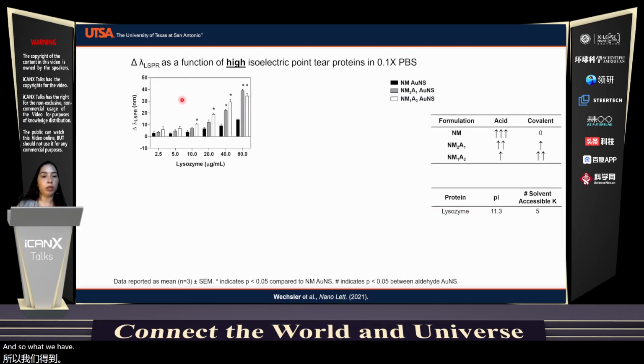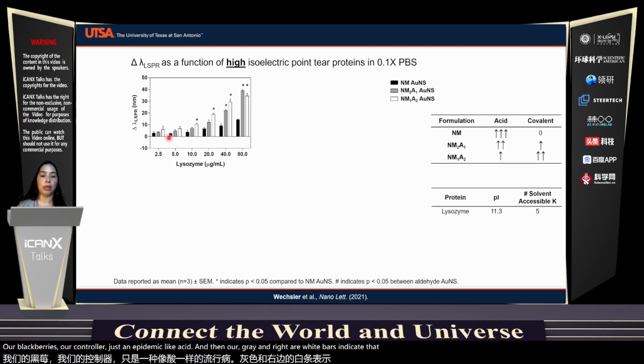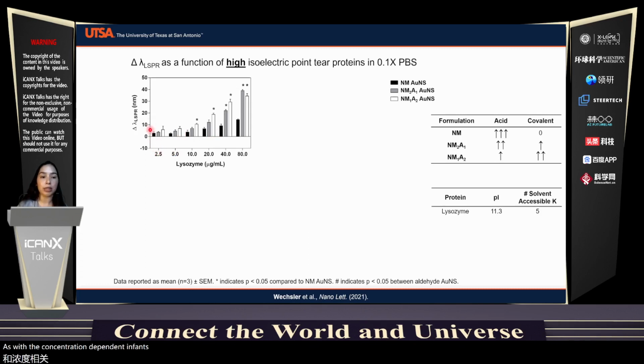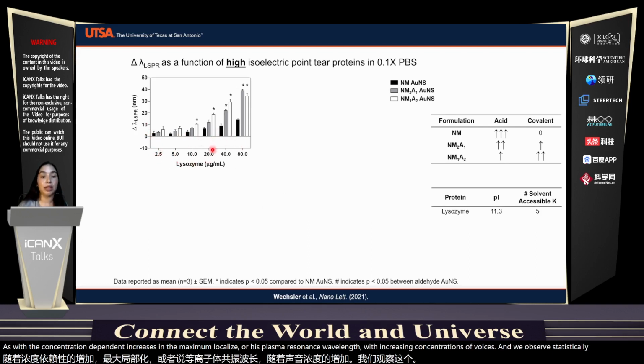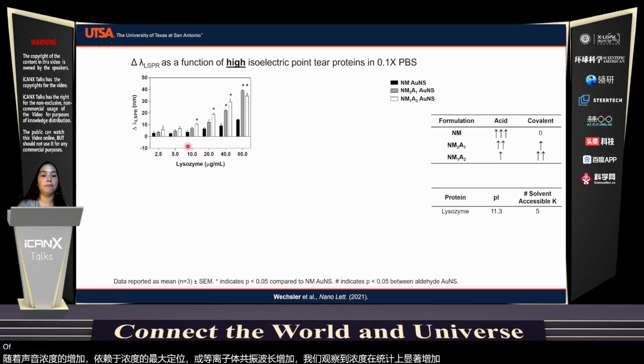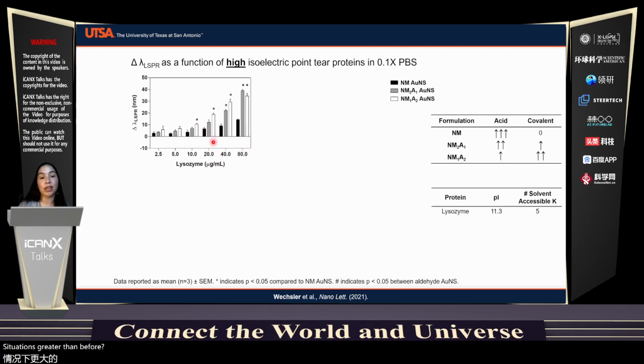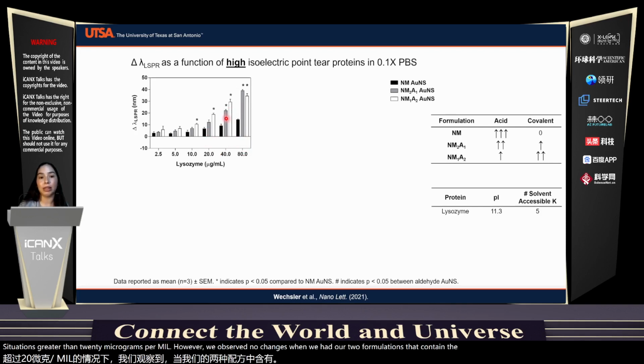And so what we observed in this first graph here is the delta localized surface plasmon resonance as a function of lysozyme concentration. Our black bars are our control, just the NIPAM methacrylic acid, and then our gray and our white bars indicate our increasing component of our covalent monomer incorporated into the polymerization scheme. And so we observe concentration-dependent increases in the maximum localized surface plasmon resonance wavelength with increasing concentrations of lysozyme. We observe statistically significant increases at lysozyme concentrations greater than 20 micrograms per mL. However, we observed no changes when we had our 2 formulations that contain the aldehyde component for lysozyme.